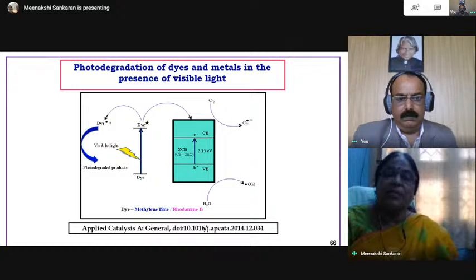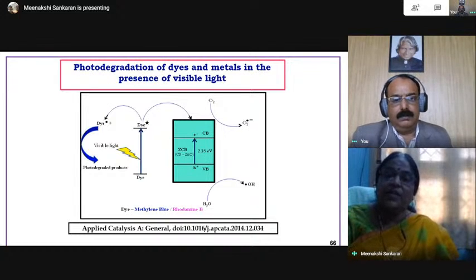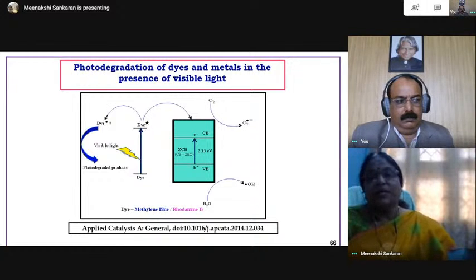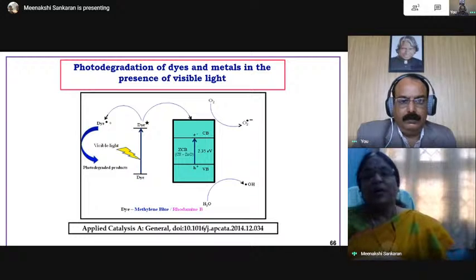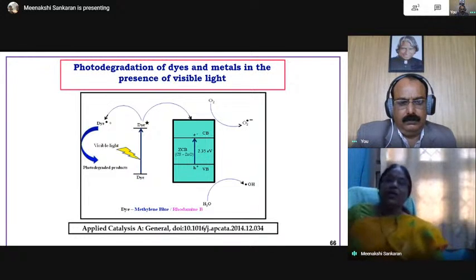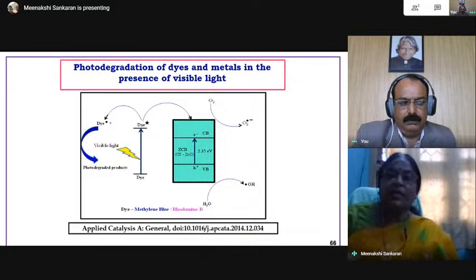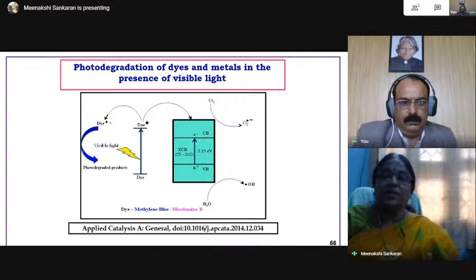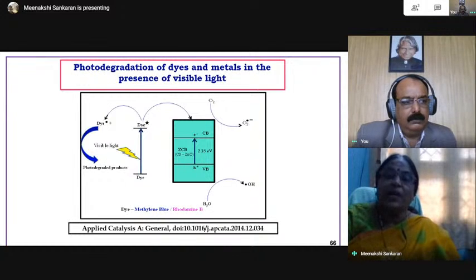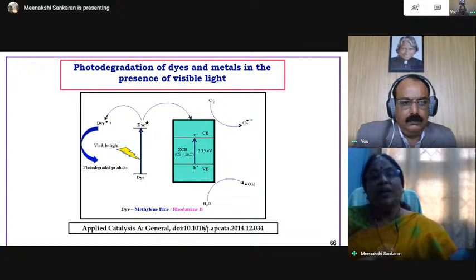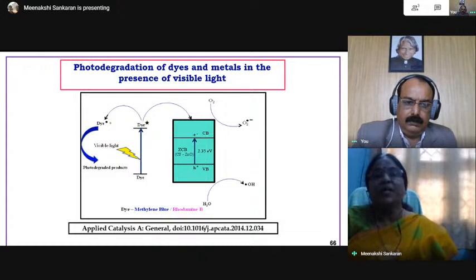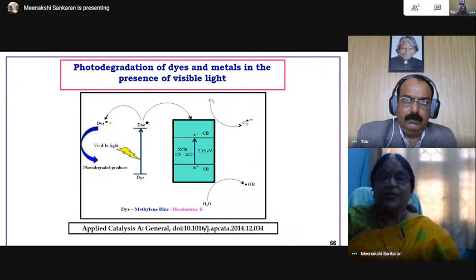Normally, photocatalysts are titanium dioxide or zinc oxide. We have selected zinc oxide because of its cost and all. So we have blended the zinc oxide photocatalyst with chitosan, and we found that this addition of chitosan reduced the band gap, so that this material is capable of absorbing visible light. So we have made this photocatalyst an absorber of visible light by mixing with chitosan. And we have carried out all the experiments in the presence of visible light, which is less harmful.